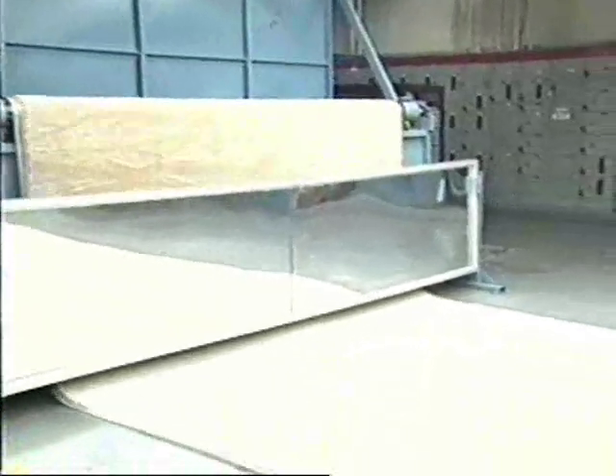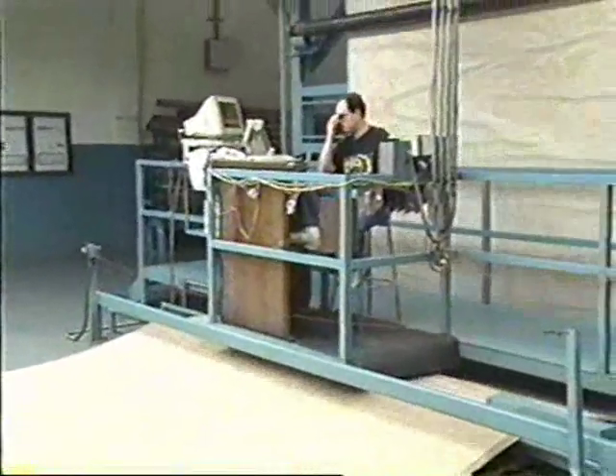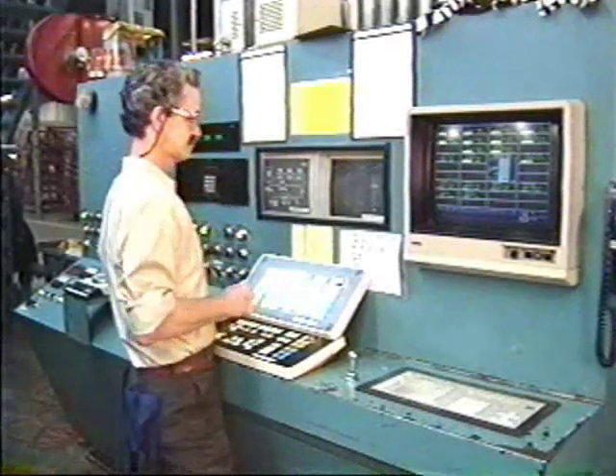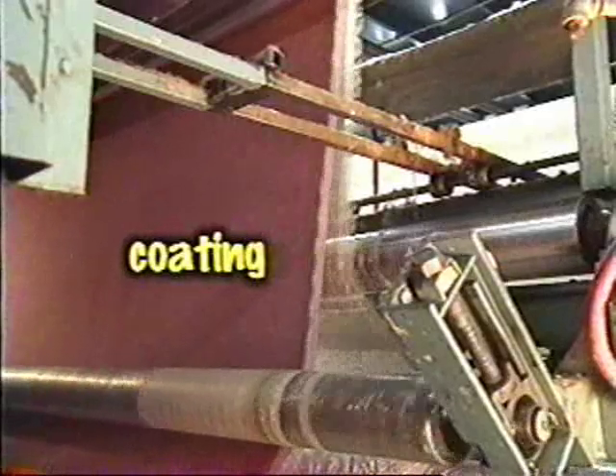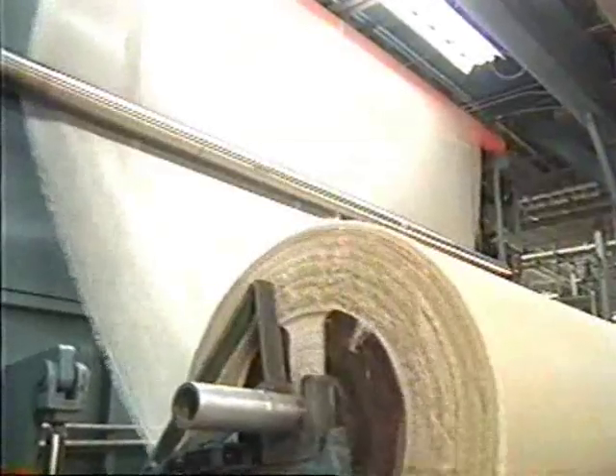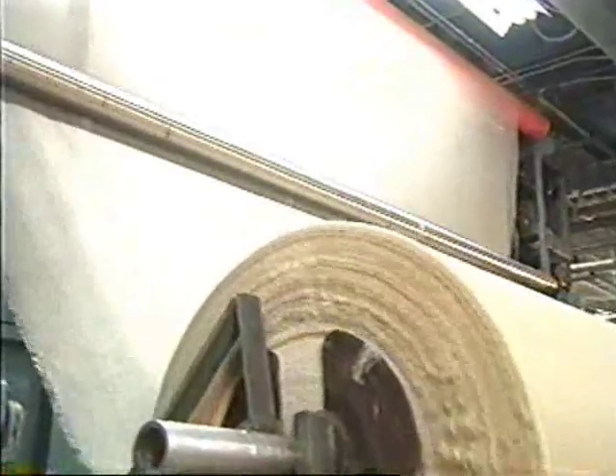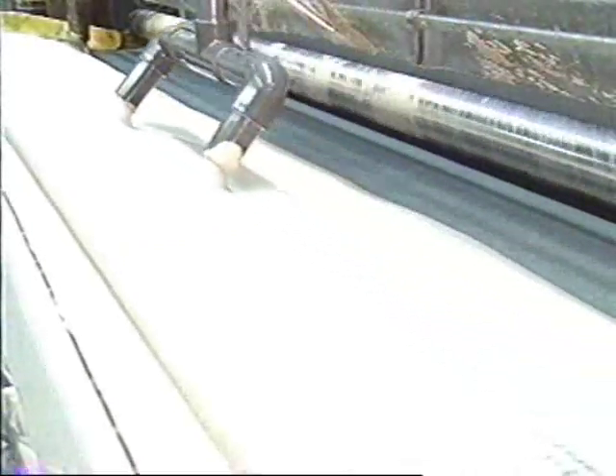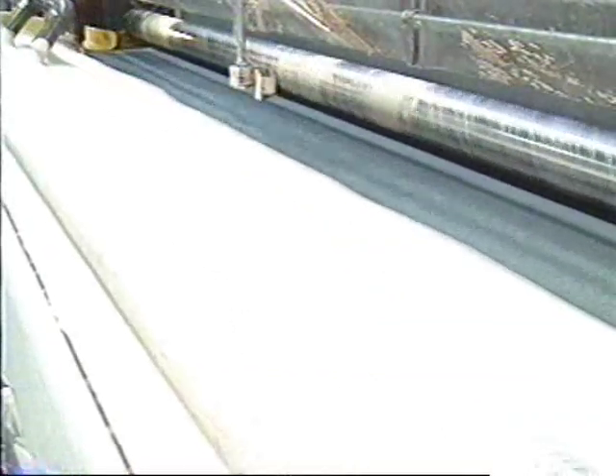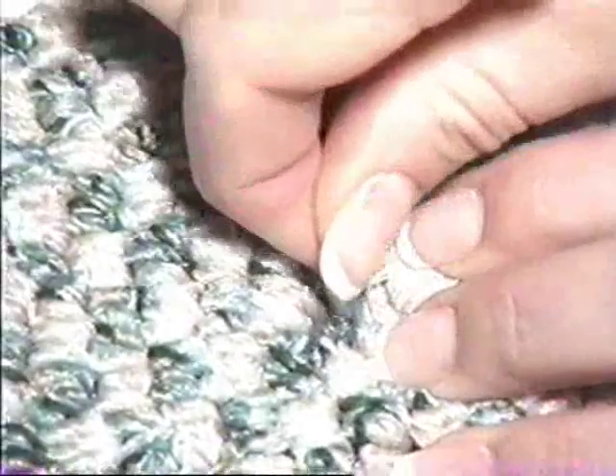Following the dyeing process, the carpet is inspected and ready for the final process: coating and finishing. While there are several steps in this process, generally all of them take place in a single production line. In the coating process, a secondary backing is added to the dyed, tufted carpet to provide dimensional stability. There are two main types of secondary backing: jute, a natural fiber, and synthetic backing made from polypropylene, which is the major secondary backing used by the carpet industry. A latex is used to bond both the primary and secondary backing together. The coating process also serves to anchor the tufts into the primary backing, which reduces fiber loss and excessive pilling, and prevents the carpet from fraying. Tuft bind, measured in pounds, determines how many pounds of pressure it takes to pull a yarn tuft from the backing.